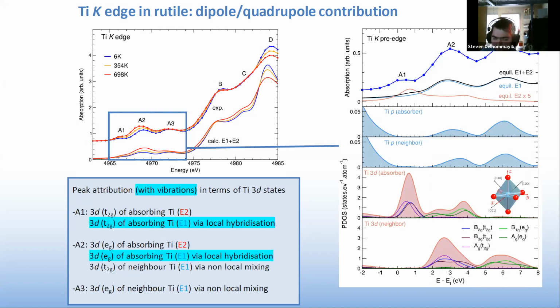And if we add vibrations, like before with aluminum, we know that it adds an E1 contribution to peaks that are supposed to represent the 3D states of the absorbing atom. We know that the vibration causes the breaking of the local symmetry of the site, which allows the forbidden local hybridization between the absorbing P and the 3D states of the atom, which is why it creates this forbidden contribution here and allows the peak to grow as temperature grows. And so looking at these two cases, the aluminum K-edge and the titanium K-edge, we could get a brief, general overview of the effect of vibration.